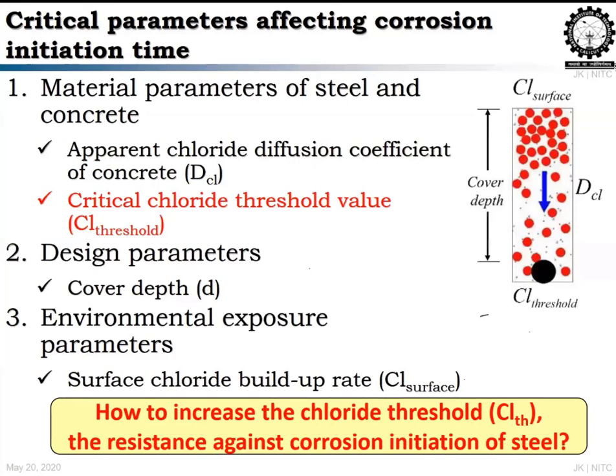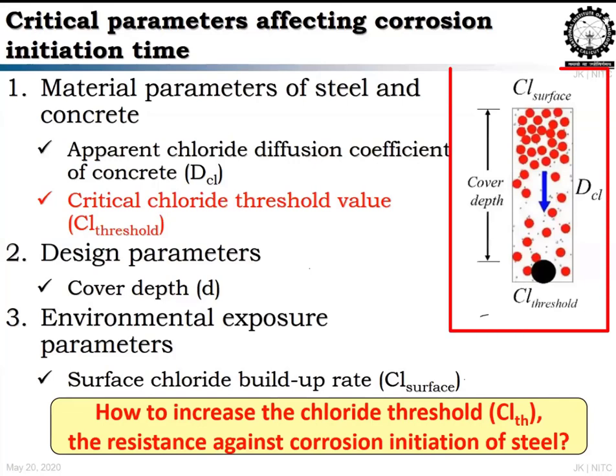So the materials which we use are obviously concrete and steel for making a concrete structure. For the corrosion to initiate, if you see the figure on the right side, there is a black round, that is a steel bar, which has a cover depth, okay, where the red dots are the expected chloride if the building is exposed to the seashore. So slowly the chloride will penetrate and reach the steel to initiate the corrosion. So the movement of chloride to reach the steel is one of the phenomena where the quality of concrete is the influencing parameter.